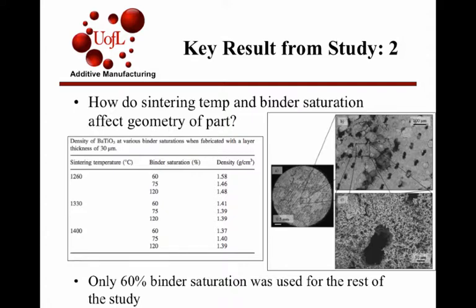So they went with a lower binder saturation to keep these holes as small as possible and keep the density high, that way to improve the electrochemical properties. And then again, the sintering temperatures here, as you can see, the lower the temperature, the higher the density. So that kind of gives a little foreshadowing into the next study,